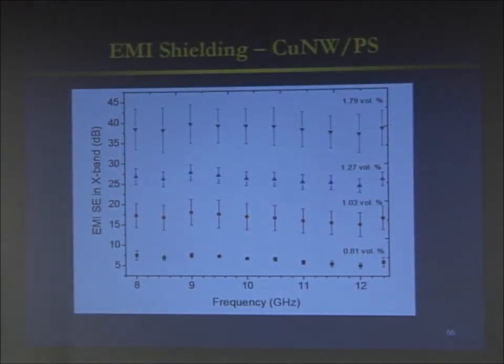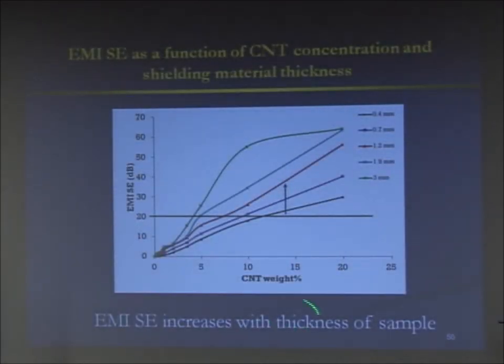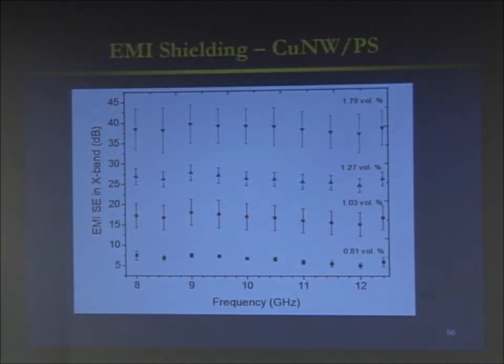Now, when we do the same type of measurements with copper nanowires, what we see here is that around 1%, if you remember in the last one, we were getting to about 10% or 15% concentration, maybe 5 for the very thick samples, where you get the good protection. Here, this is for the thinnest sample. At 1%, we're already at the stage where we can start to look at using these. This is not even 0.4, this is 0.2 millimeter, so it's half of the smallest thickness I was showing in the previous plot. Typically, the thickness is about 10 times more to get the same type of